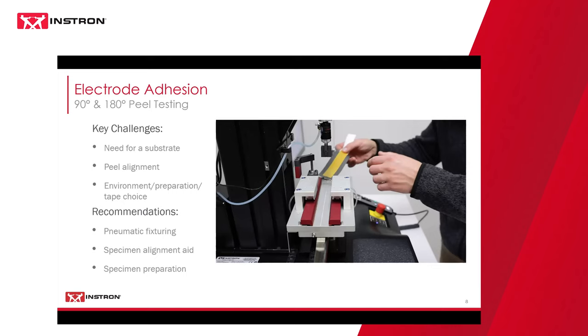The first challenge between these two variations of peel testing is in regards to the need for a substrate. For those of you that don't know what a substrate is, it's a rigid body material that you would adhere your anode or cathode to because your anode or cathode is too delicate. So in this case, we typically recommend a mirror-coated finished substrate, like a metal substrate that you would adhere an anode to. For 180-degree peel testing, it always requires a substrate. You need that rigid material to attach your cathode or anode to in order to maintain a proper 180-degree peel throughout every test. If you don't use one, you'll see the material just kind of flops around as it goes, and we would never recommend that. That's not how you get repeatable results for your testing.